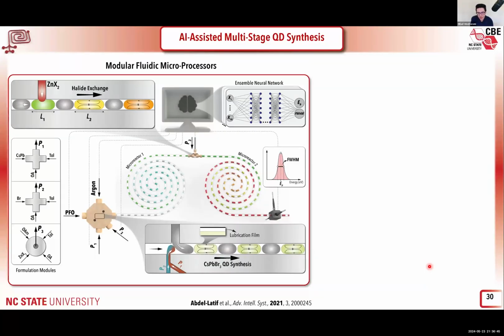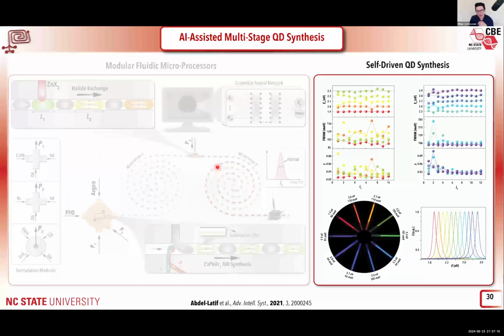Later on, we upgraded the hardware. We wanted to show we can actually do multi-step synthesis. In this case, we have 2 flow reactors that we can synthesize, for example, green emitting quantum dots in reactor 1, and then we can do a band gap tuning in the second reactor through halide exchange reaction. And there's a lot of fluid dynamics behind here, how you can actually do reliable 24/7 operation here. I'm not going to go through details of that, but it's a very rich 3-phase flow dynamics here. And then in this case, we showed the 9 inputs, 3 outputs, and active learning. Again, using Bayesian optimization, they could discover the synthetic route of any target emission color within only 40 minutes.